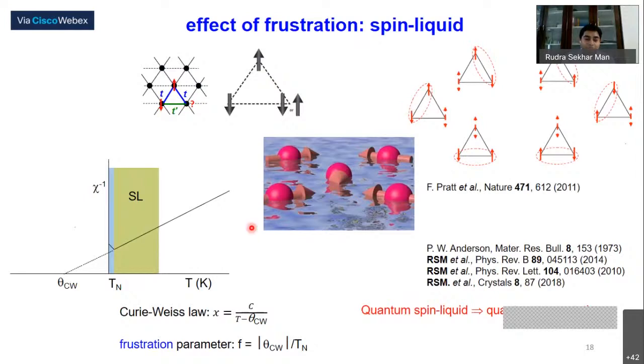And that kind of thing gives you a spin liquid phase. So normally, what do you expect, and what is the signature? The moment you have antiferromagnet, you have strong correlation between the spins. You expect that if you cool down the temperature, at some point you get a phase transition to the antiferromagnetic order. But in this case, because of this frustration, the system doesn't know. If you go to very low temperature, the system doesn't order, or in case it orders, it is very low compared to the Curie-Weiss temperature. So the more frustration, the less magnetic order there is in the system. That means the frustration parameter goes infinite.